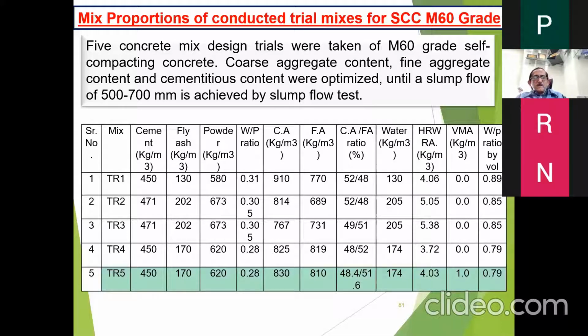Then the water content, you can see, was 174 kg, with high range water reducer of 4 kg per cubic meter, and the VMA 1 kg per cubic meter.